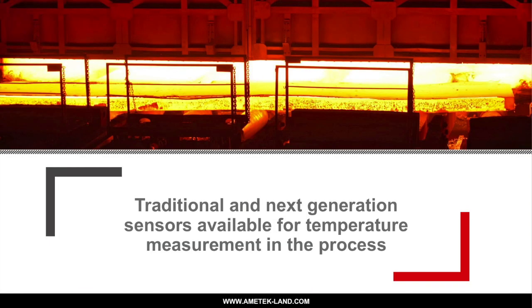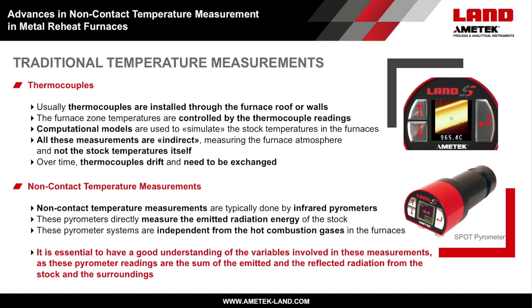What are the traditional and next generation sensors available for accurate reheat furnace temperature measurements? Commonly used thermocouples are installed in most furnace types, and the furnace temperature zones are usually controlled by the temperature readings. Based on calculated models, the temperature of the stock is then determined, while the thermocouples are installed penetrating through the furnace refractory wall, measuring near to the internal refractory surface. These measurements are of course indirect. It means they measure the furnace gas temperatures, but not the direct object or stock surface temperatures. These need to be calculated based on those model calculations.